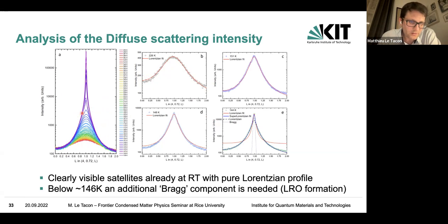But as you cool down, at low temperature this is not a Lorentzian anymore. Below roughly 146 Kelvin, you have to fit this peak with a combination, what is called a super Lorentzian. You have to fit this with a Lorentzian for the diffuse background and a resolution-limited feature that corresponds to a long-range order Bragg peak. So in other words, you can see from the diffuse scattering really nicely the difference between the fluctuating part and the long-range order part.